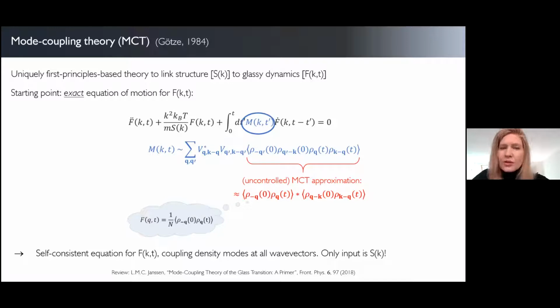And importantly, the only input that the theory needs to solve this equation and predict the dynamics is the static structure factor, which is essentially your boundary condition at time equals 0. So the static structure factor appears here and also implicitly in these vertices here. So once you know the static structure factor for all relevant wave vectors of your favorite system at any given temperature and density, you can plug that into this theory and then solve this equation self-consistently to get a prediction for the dynamics. All right, that is mode coupling theory in a nutshell.